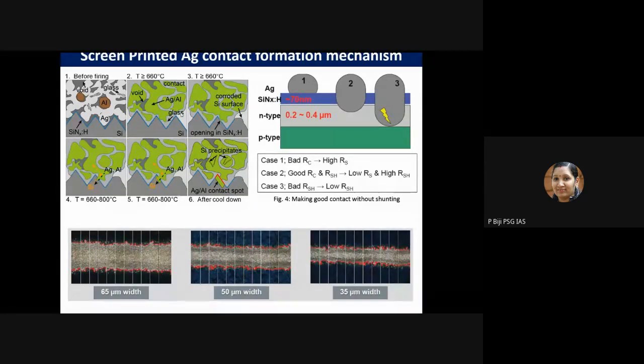Using screen printing, you can see that finger lines up to 35 micrometer width have been printed at this point of time by the latest screen printing technology. So again, advancements are happening. If they are able to reduce the finger width and aspect ratio further, then the technology is okay, good. But still, if you are thinking about cost reduction, you definitely require an alternative metallization process.